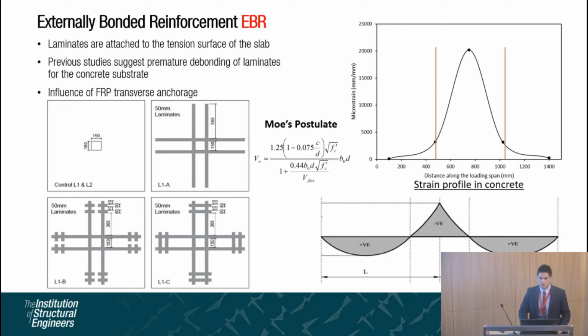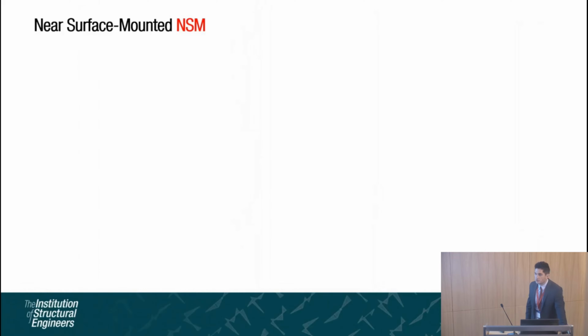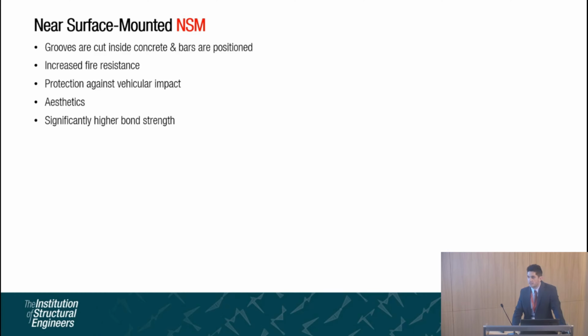Based on Moe's Postulate, because these are acting as flexural reinforcement, it will be contributing to the punching capacity. The second method that we used was a near surface mounted method. In this method, grooves are created inside the concrete and FRPs are attached using epoxy adhesive. The remaining cavity is then filled and leveled.